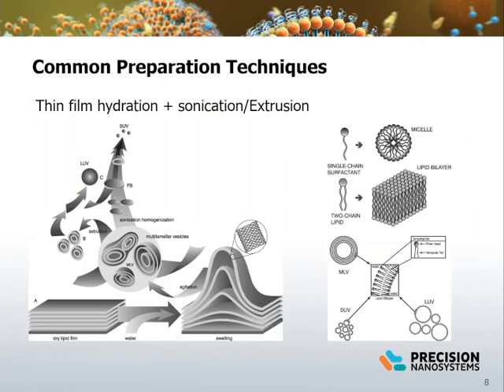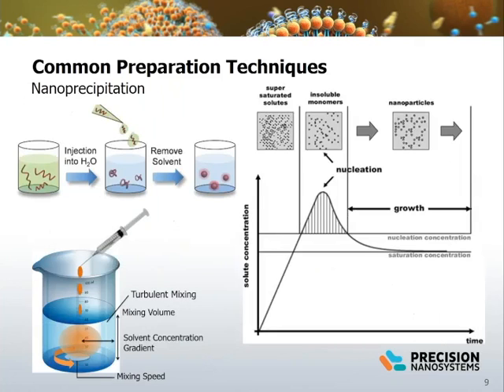Traditional techniques of forming liposomes include thin film hydration, where thin lipid films or lipid cakes are hydrated forming large multilamellar vesicles. Once these vesicles have formed, reducing the size of the particle requires energy input in the form of sonic energy by sonication or mechanical energy by extrusion.